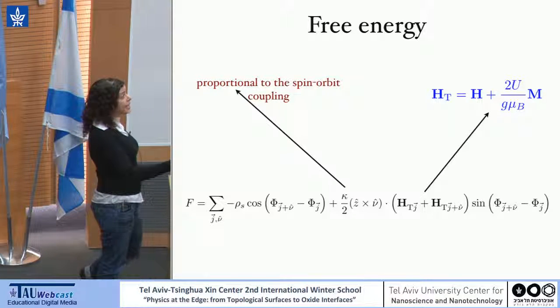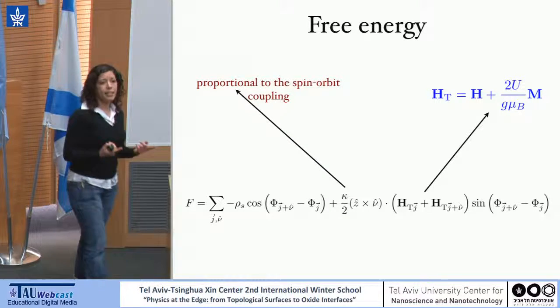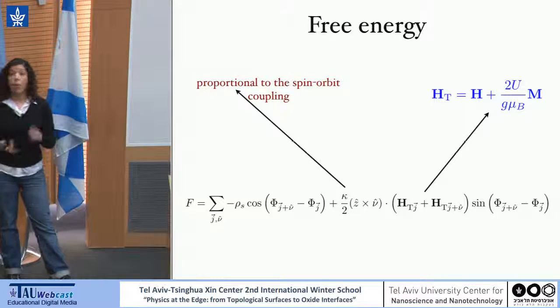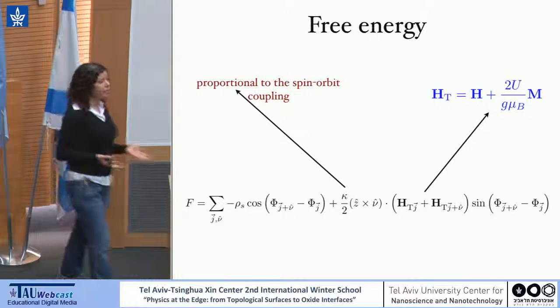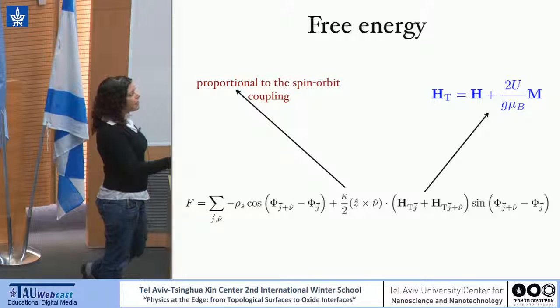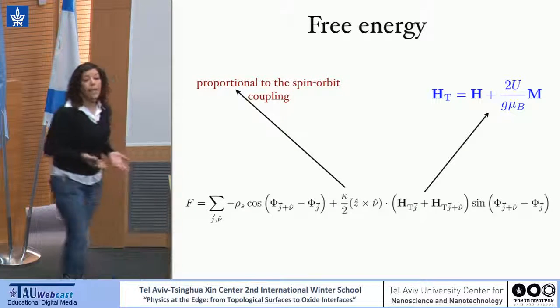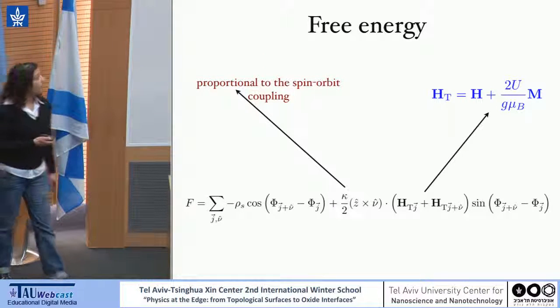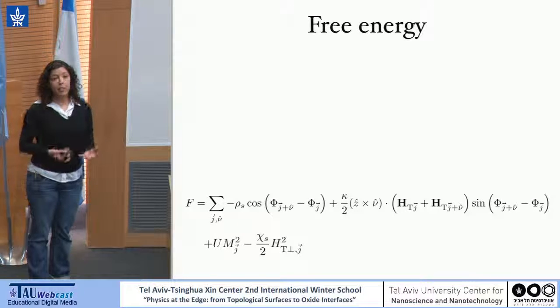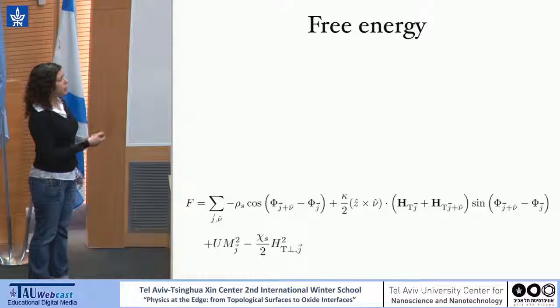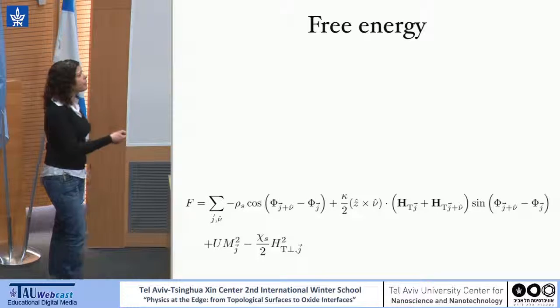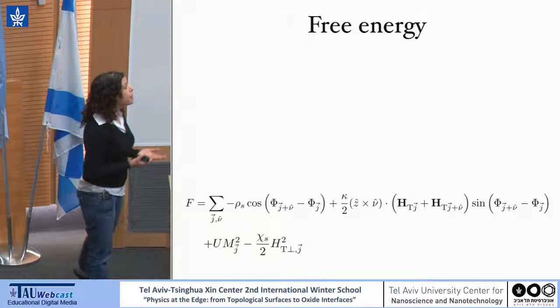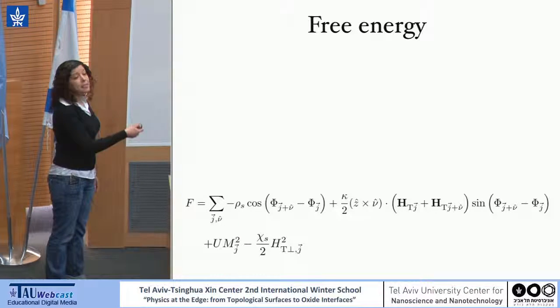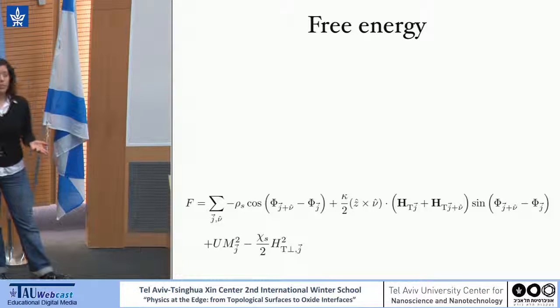And it basically couples the magnetic field, which is here the total magnetic field, either external or any kind of magnetization field, to the gradient in the superconducting phase. Now, in addition to these two terms, we should have the mass of the magnetization fluctuations that we consider, but also the spin susceptibility of the system.